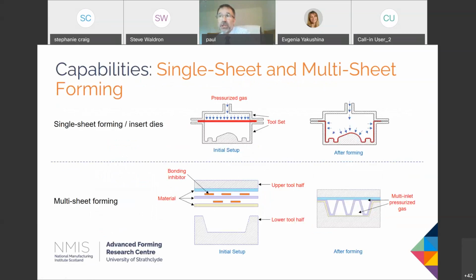So let's say the 3 sheets of titanium 64, they will have gone through a careful cleaning process to make sure that the surfaces are nice and clean. And then what we would be doing there is applying a bonding inhibitor, or more generally known as a stop-off material, that inhibits bonding in certain areas. And that's important because we want those areas later, they become basically the gas paths for when we then subsequently inflate the part to form the sort of shape that you see on the right.